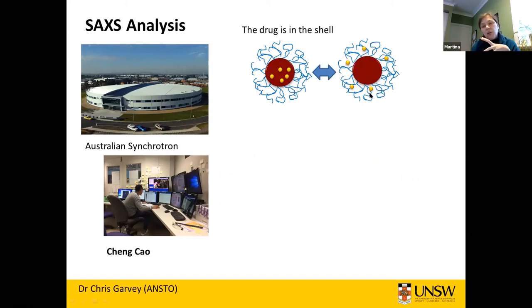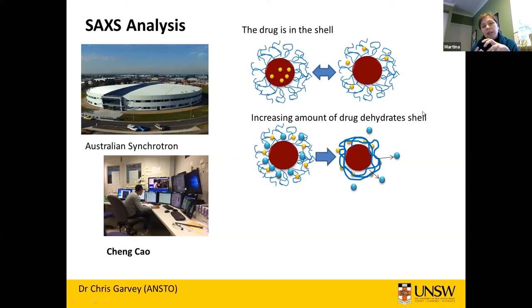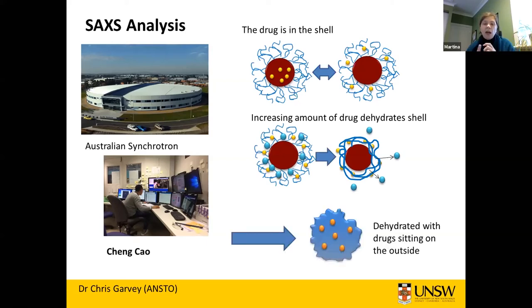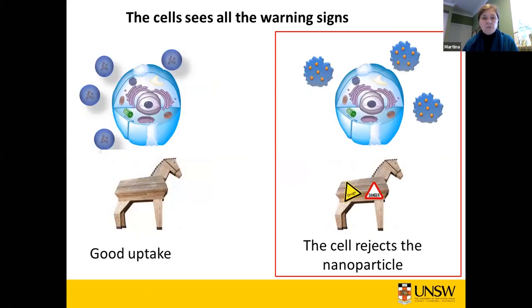And by leaching into the shell, what happened is it dehydrated the shell. So suddenly our shell became actually quite hydrophobic. And the reality is what our cell is seeing, it sees sort of a quite dehydrated nanoparticle with the drug sticking out like a little warning sign. And so really, that's what we were hoping for, sort of a good uptake with increasing amount of drugs. And this is actually what we saw.